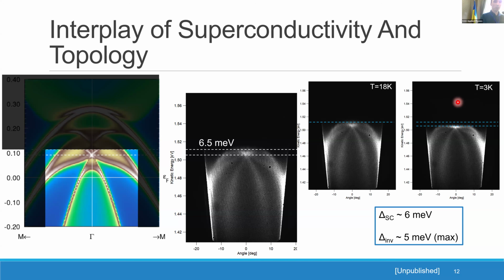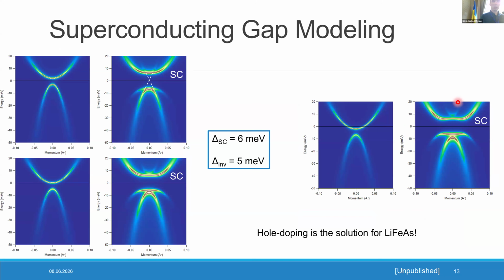And to figure out in more detail what is happening, we tried to model it. I didn't put any formula here, but luckily the previous speaker also mentioned it very nicely. ARPES gives us essentially a spectral function, which is the imaginary part of the Green's function of quasi-particle interactions. In that regard, it's easy to write it analytically, and this is what has been done. So these spectra are an analytical formulation of two bands, which are separated by 5 meV. In this case, we call it the inverted gap. And the superconductivity that we induce is 6 meV by a simple BCS model.